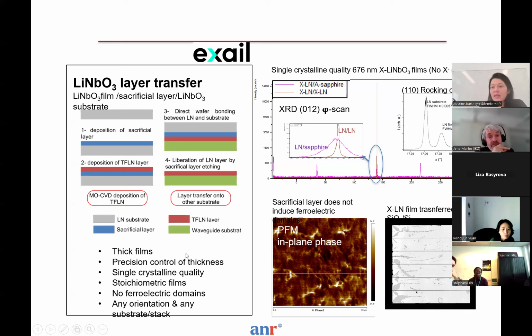So basically we can grow any orientation, and the thickness depends on time and so on. The roughness is still significant, around 6 nanometers, so probably we can do polishing. And we have some layer transfer results on silicon dioxide, but there were some problems with the silicon dioxide quality, because the Piranha etch started to etch the silicon dioxide. But these were the first results where we transferred. All the process, bonding and so on, is done on 4-inch wafers, but because we cannot etch the whole lithium niobate substrate, we dice it into smaller pieces to liberate the film faster. Here you see the diced pieces.